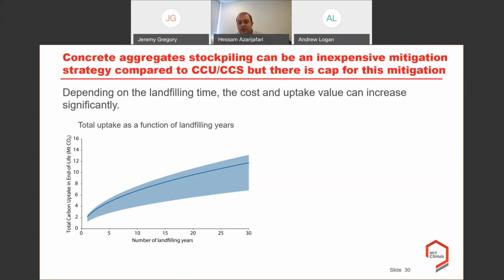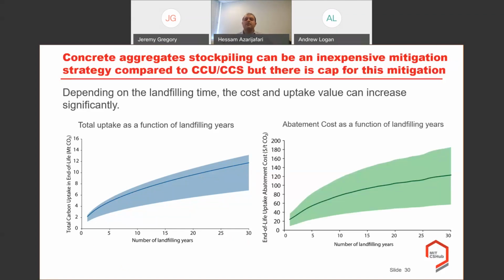And if you want to estimate the cost associated with that, the cost of renting the landfilling site or occupying that landfilling site can vary significantly from one location to another. This cost can vary from $20 per ton CO2 savings, what we call abatement cost, and can be as large as more than $100 per ton CO2 in the future. And here is the current cement carbon capture storage cost that was reported in different policy reports, which is around $75–80 per ton CO2 captured. So for the moment that this technology is still expensive and still under development, we can definitely consider the end-of-life uptake as a meaningful and cost-effective strategy to capture the CO2 naturally.